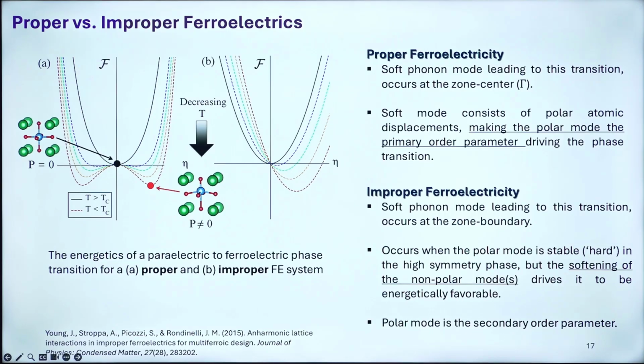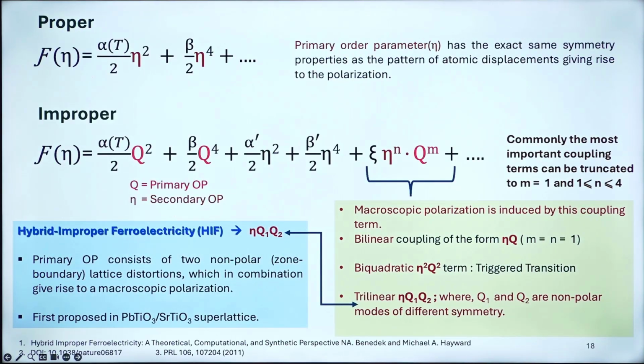it can occur at zone boundaries, not necessarily at the gamma point, and it can be at X, M or R, any other point of the Brillouin zone. This occurs when the polar mode is stable in the high symmetry phase, but the softening of the non-polar mode drives it to be energetically favorable at some other point of the k path of the Brillouin zone. So now here the polar mode is the secondary order parameter.